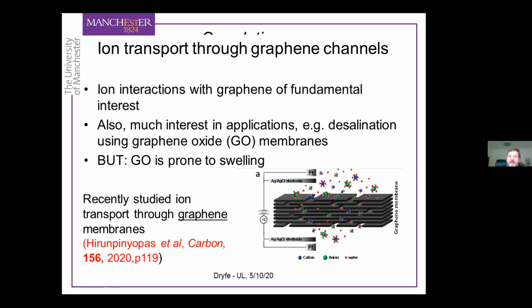So there's a paradox there, and nobody's really resolved that paradox very successfully. But we're interested in using other 2D materials for these types of applications. In fact, we've done some work recently on molybdenum disulfide, which is very promising in this context. I won't talk about that here, but we've also done some work on graphene rather than graphene oxide, which is less hydrophilic than graphene oxide, but it's not prone to swelling. So you don't have the swelling problem with graphene membranes.